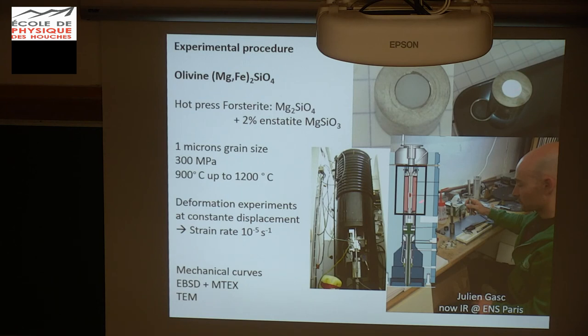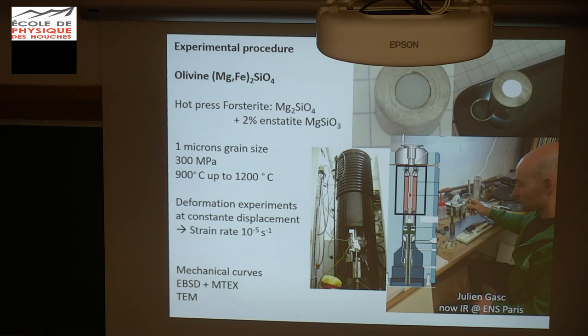The sample is basically one centimeter in size, and the diameter is about seven to eight millimeters. It's a very nice apparatus to do deformation in almost geological conditions, because we have an internal furnace as well as an internal load cell, which permits us to reduce thermal gradients as well as all the friction you can have in a normal apparatus. The most important parameter is Julien Gasc, who did the postdoc with me in Montpellier and is currently taking up one of the experiments.